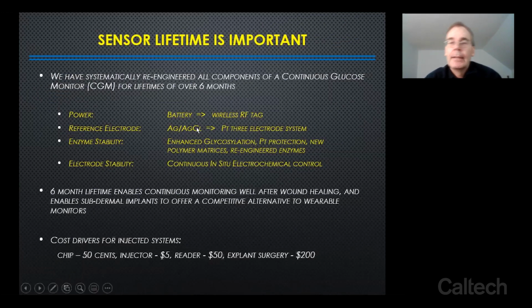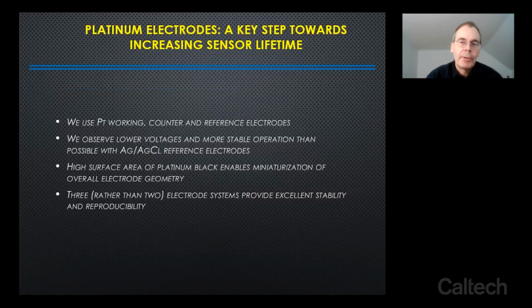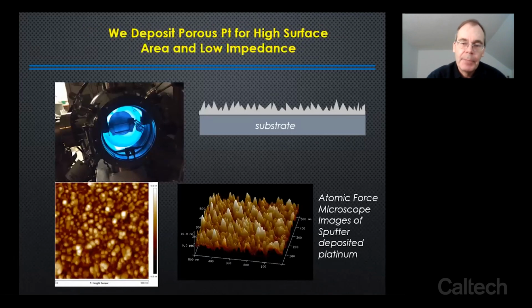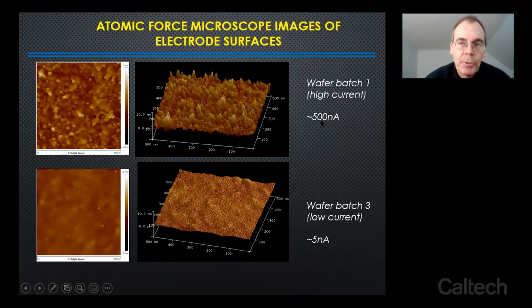We try to avoid conventional reference electrodes because silver chloride only lasts for about a month. And after that, it strips all the chloride and the silver away. And so instead of that, we use platinum. So we had to reinvent a really old electrochemical system. And we did so by changing materials out, swapping things, but making them compatible with microelectronics. Okay, so for example, platinum, instead of using a normal platinum deposition system that would give you a nice smooth layer, we actually modified everything so that we could get a very, very porous layer to increase the surface area, because the surface area, as shown here, gives you about 100 times more sensitivity and current than you would if you had a smooth layer.